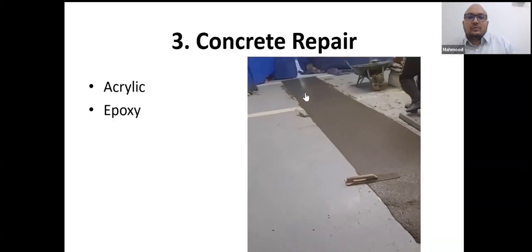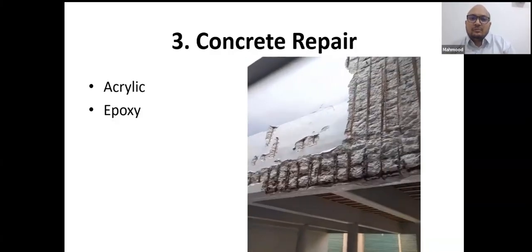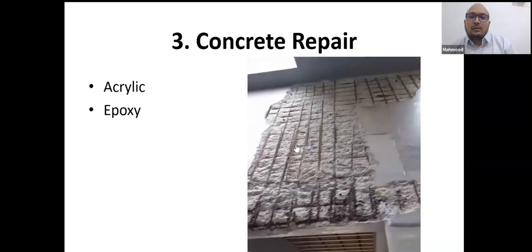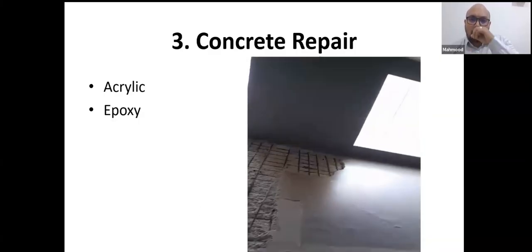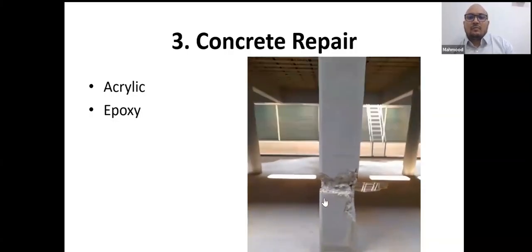There are various polymer modified concretes. See, this is honeycombing, where they repair with the same epoxy bonding agent with polymer modified polypropylene fiber reinforced material. It is shrinkage compensated polypropylene fiber reinforced cement, okay. It's used for structural repair of honeycombing. This is a cooling tower.